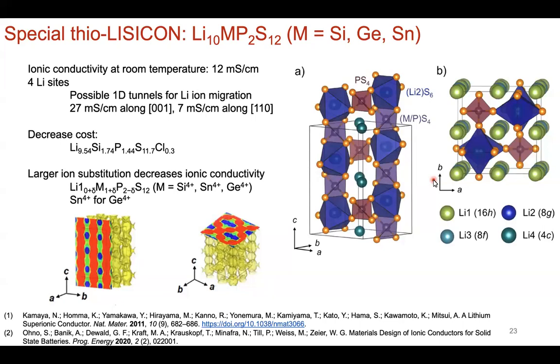And in fact, you sometimes get decreased ion conductivity as well as decreased chemical stability at the interface with lithium, because you get decomposition products that are lithium silicates. So ternary and binary compounds that are easy to form, thermodynamically, energetically favorable, that are easy to form at the interface. And so there's still a challenge to actually incorporate these solid electrolytes into an all-solid system. But in terms of driving ion conductivity higher and higher, these are quite high.